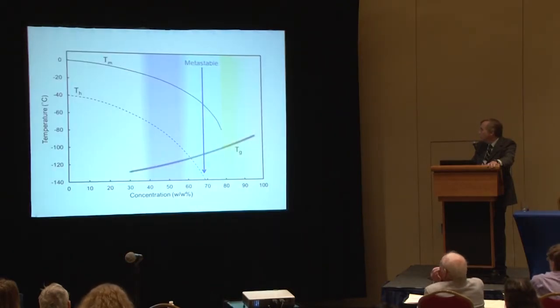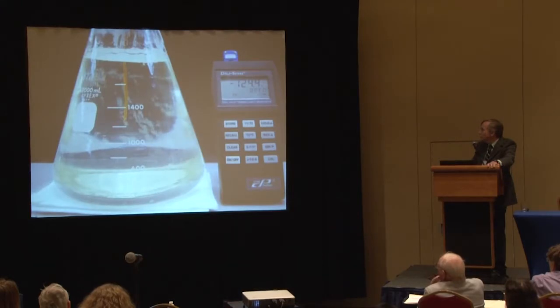And at still higher metastable concentration, you can do tricks like this. This is 2 liters of the M22 vitrification solution that we now use for preserving tissue at 21st Century Medicine. And you can see the thermocouple probe in the middle of the solution there, showing that this solution is actually at a temperature of minus 124 degrees Celsius, below the glass transition temperature. This entire solution volume is vitrified, fracture-free even, and I'm keeping it clear in room air by having the surface coated with methanol so it isn't frosting up.